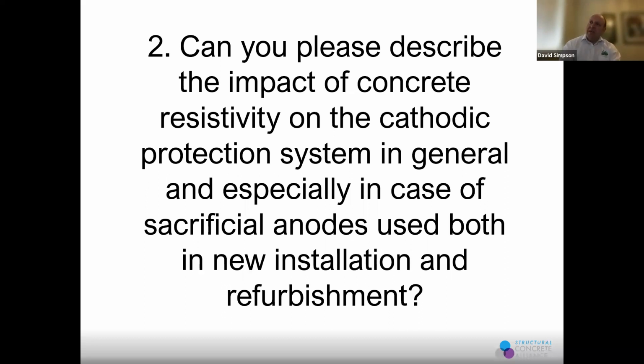But over the past 20 years, I think that's changed, and most material manufacturers now state up to 50 kilo-ohms per centimeter, which is much higher. And I think that really covers most flowable and most hand-applied materials. I think typically you'd want to keep away from anything that's epoxy or insulated, like mag phosphate materials, because those are insulative and are not compatible with cathodic protection, really. So I hope that gives you a bit of a rounding one for me.